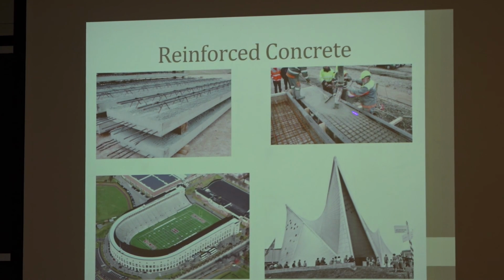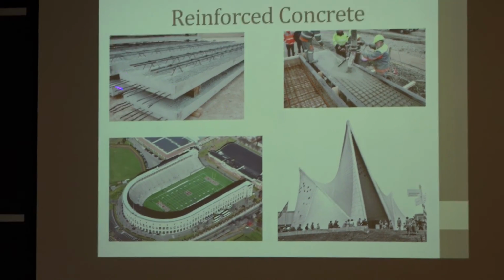You don't have to have steel rebar, but you can actually see on the tensile side of this beam, you've got the steel bars on the tensile side. You don't put them on the compression side because concrete's fine in compression. It's all fracture mechanics here, right? The Griffith equation and stuff. So it has to be about 5 or 10% cross-sectional area of steel compared to concrete, because steel's about 10, 20 times stronger than concrete. Concrete typically, 30 days after pouring, has about a 3,000 psi compressive strength. Steel's 30, 60,000, pick your number.